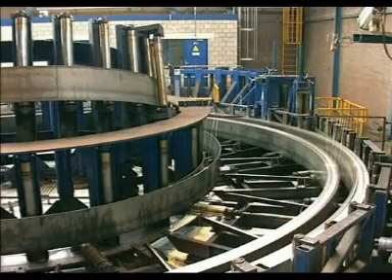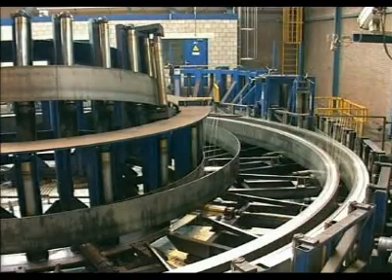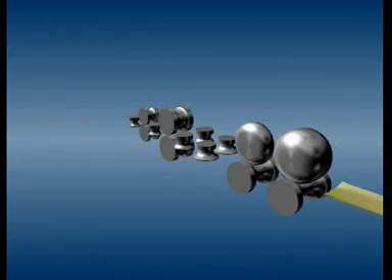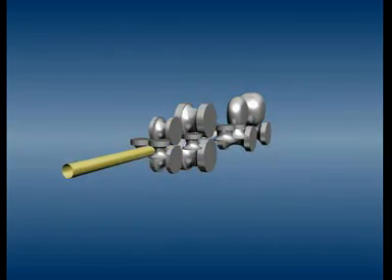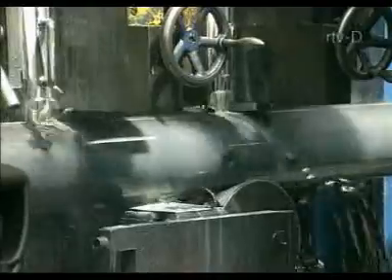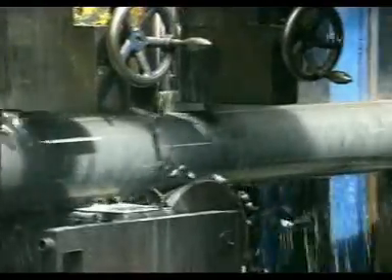The strip is passed through a series of rolls to form a required profile. This can be any shape or size and is limited only by what is physically possible. After forming, the tube is passed through a high-frequency induction welder, where the strip edges are joined together to form the final circular or rectangular profile. Immediately after welding, the external weld flash is trimmed to leave a smooth tube.